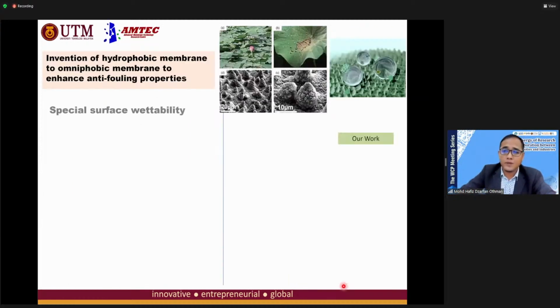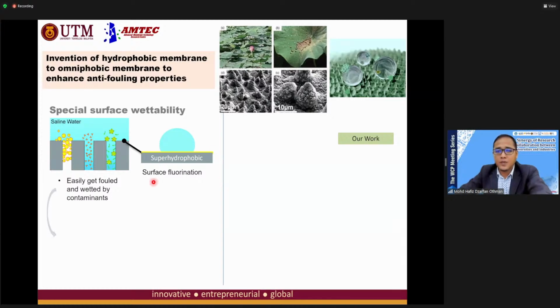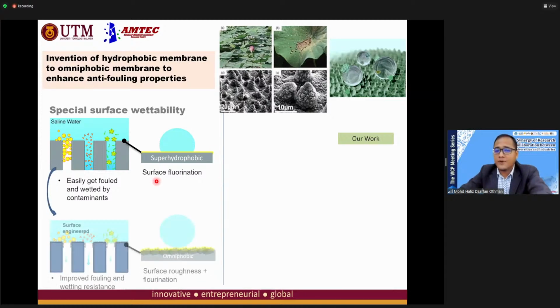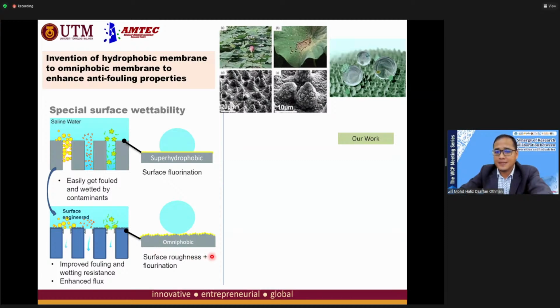We were inspired by the lotus leaf structure, because the lotus leaf has very high nodules, and these nodules can prevent water molecules from having close contact with the membrane surface. So instead of having only the FAS immersion method to do fluorination on the membrane to obtain superhydrophobicity, we actually do the roughening on the membrane first, before we do the fluorination. And this is what we call an omniphobic layer membrane.